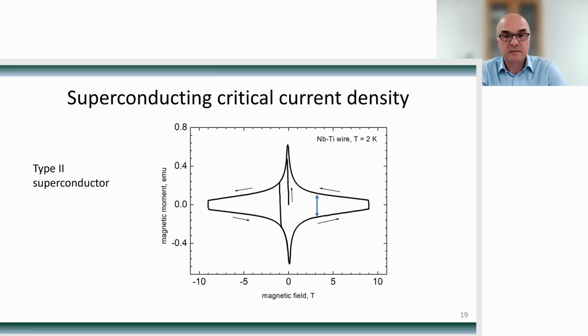It's an alternative method, and the way I see it, the vibrating coil is simply more complicated from the engineering point of view. The vibrating coil method will depend greatly on how homogeneous the magnetic field of your superconducting solenoid is. For VSM systems, we make higher spec homogeneity magnets. But still, if you imagine that you're moving the coil, it will inevitably sweep a little bit of the decay of the magnetic field of the solenoid. So it becomes more sensitive to unwanted signals. And that is the answer.